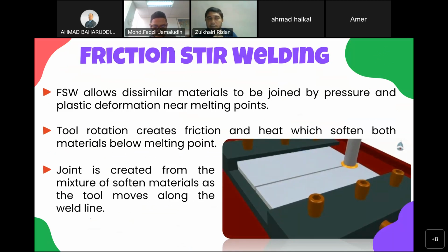So because it allows the dissimilar materials to be joined by pressure and plastic deformations under the melting point, as can be seen by the animation here. Friction stir welding works by using a rotating tool, which is rotated and plunged into the interface of two workpiece. The tool is then moved through the interface of the workpiece, and the frictional heat cause the material to heat and soften. The rotating tool then mechanically mix the softened material to produce a solid state bond.